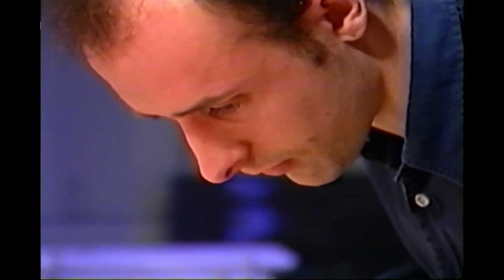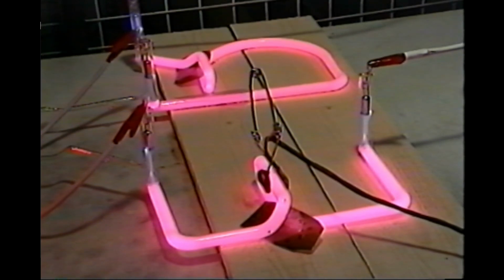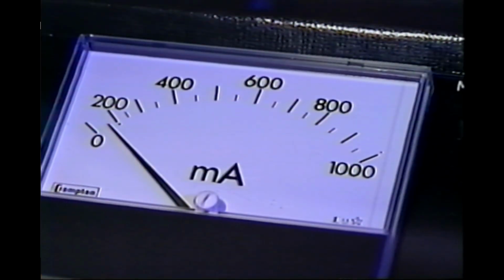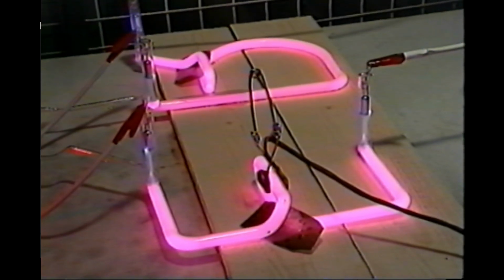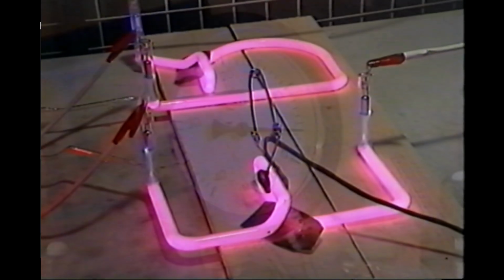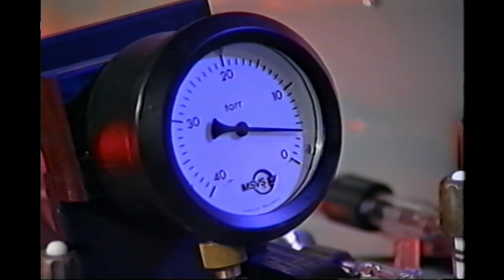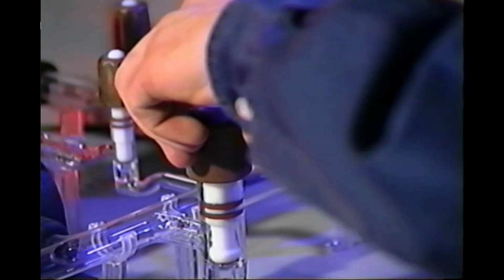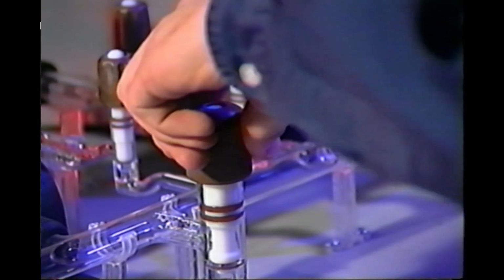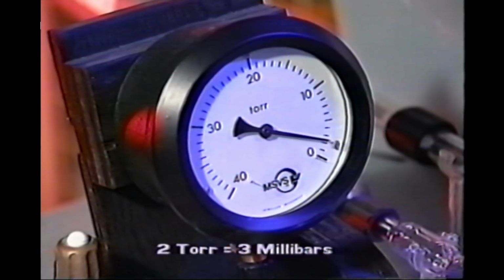If the pressure is allowed to continue falling, a flashback down the glass manifold can occur, leading to possible equipment damage. Increase the current to 150 milliamps. As the tubes begin to heat up, the pressure will increase slightly due to vaporization of moisture. By briskly opening and closing the main stopcock, the pressure can be reduced to 2 torr.